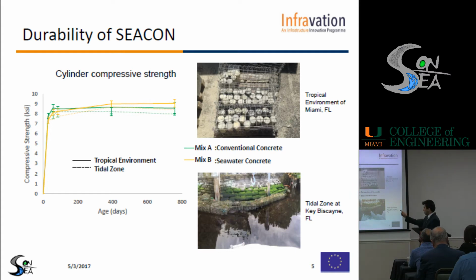So you can see on the graph, that's the age in days. We tested our samples after 28 days of moisture curing, and after that, we moved the samples to those two environments. After a year, you can see that they perform really comparably. You don't see that much effect of the environment, nor of the seawater concrete. Mix B, the yellow one, actually had a higher compressive strength over 1 year. And then at 2 years, your seawater concrete, mix B, is still higher. The solid line is the tropical environment, and the dashed line is the tidal zone.